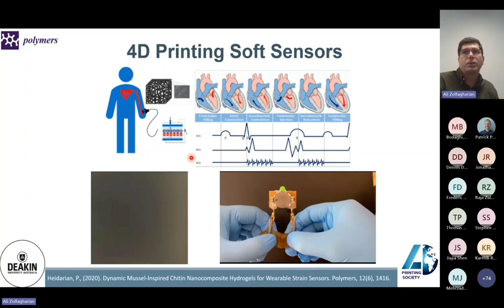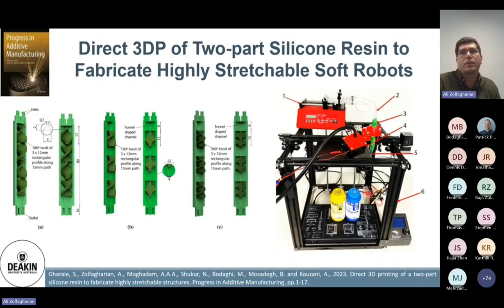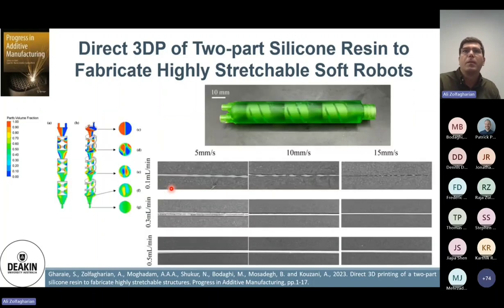And this is the silicone 3D printing that I talked about. We modified one of the common 3D printers in the lab, and we could do silicone printing. Indeed, our main novelty in this work was the nozzle, and we used CFD analysis in order to come up with the nozzle that gives the most optimized performance in terms of the extrusion and rheology of the silicone. Then the optimization was done in order to achieve the most optimized strength from the silicone.